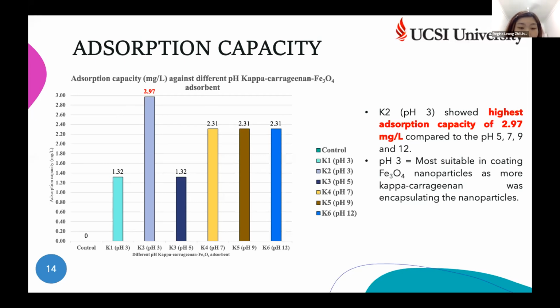And we can also see the adsorption reduced at pH 5. This might be because the positivity of the iron oxide reduced, so the ability to attract the Kappa-carrageenan also reduced. Hence, the adsorption capacity also reduced. But there's a sudden increase following pH 7, 9, and 12. This might be because the iron ion self-precipitated, forming iron hydroxide in the alkaline solution. Thus, we suggest that pH 3 is the most suitable pH for coating the iron oxide with Kappa-carrageenan.